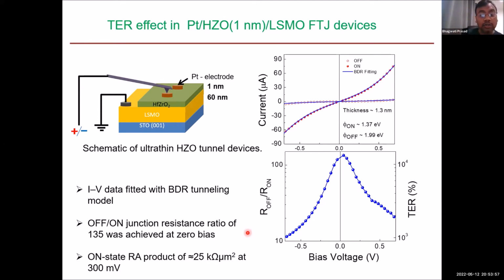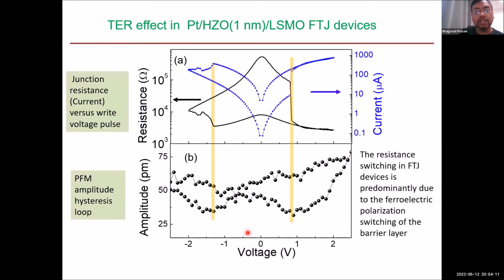The purpose here is how to reduce the RA, and that can be achieved when you make the tunnel junction thinner and thinner. If you can go below 1 nanometer, even 0.5 nanometers, then this can go further down, and then it can compete with the MRAM structure basically. This is also further proof that the switching in the device is related to the ferroelectric properties of the barrier. This is the ferroelectric amplitude versus voltage measured by PFM. Here we see that the switching matches with the resistive switching in the device. That means the switching that we see in the device is related to the ferroelectric switching in the barrier layer.